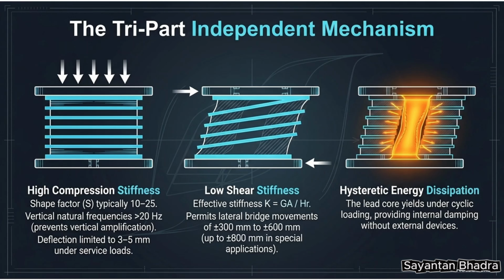The tripartite independent mechanism. The operational physics of an LRB relies on three distinct structural actions working simultaneously. First, high vertical compression stiffness is governed by a shape factor between 10 and 25, yielding vertical natural frequencies above 20 Hz to prevent vertical acceleration amplification while constraining surface deflection to 3 to 5 millimeters.